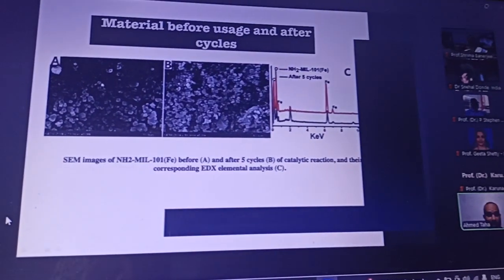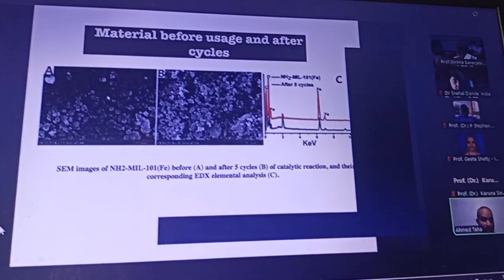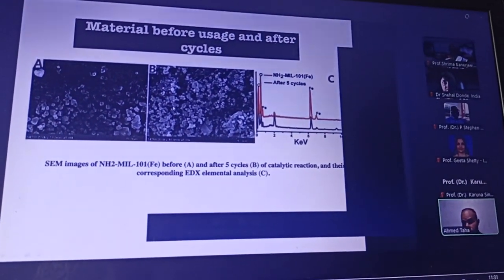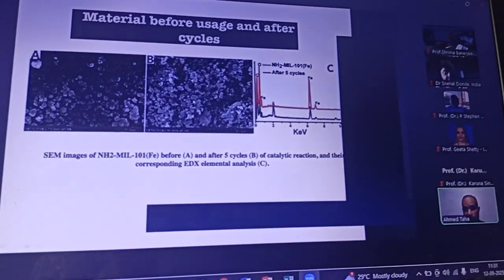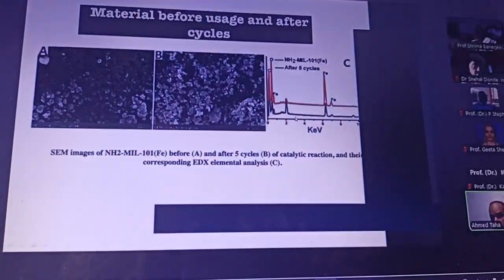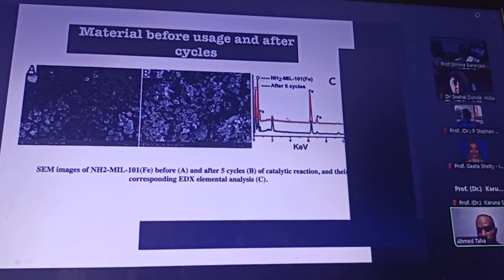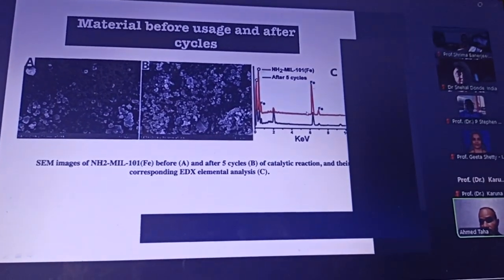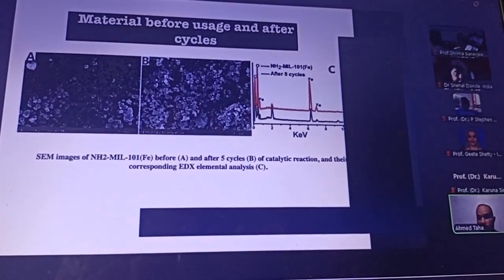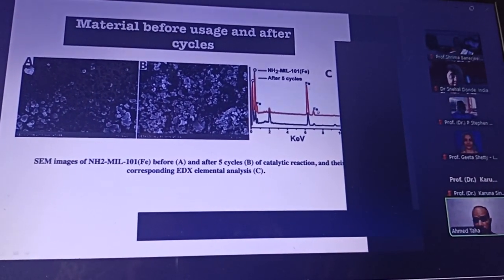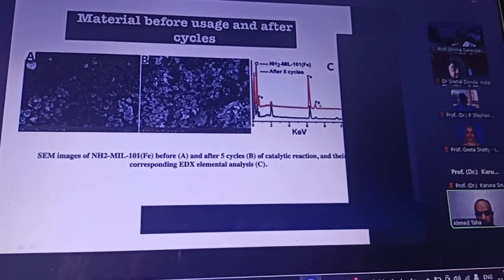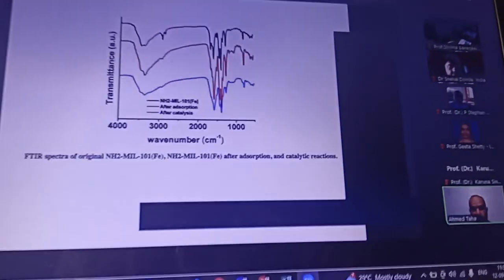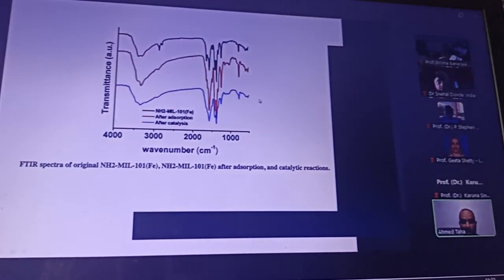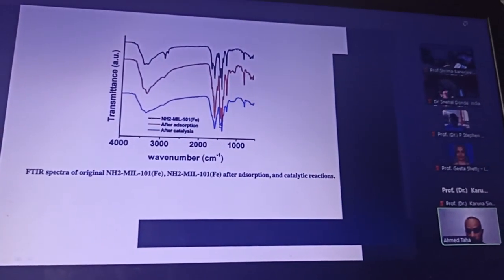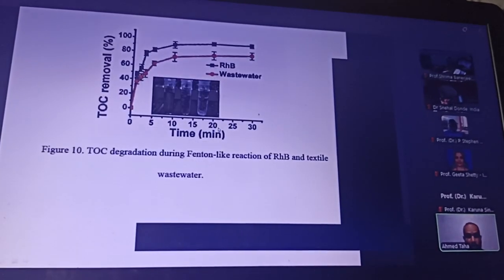So we also look at the material before and after. We look under the microscope to see the material before and after. It's still intact and in good shape. We also did EDX, to see the elemental analysis, and our elements are still there in this material after the 5th cycle, and it still can be reused again. This is the FTIR, which also tells us the structure. The amine group is still there, so the material is still working fine.